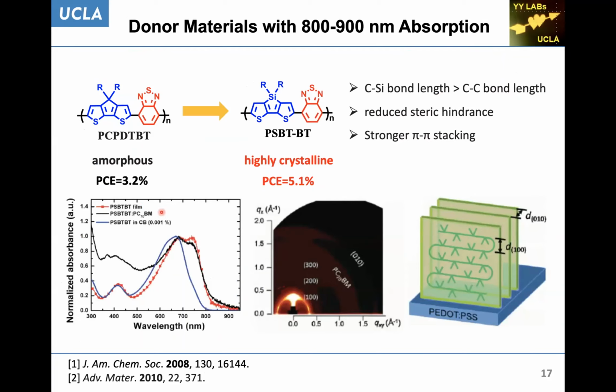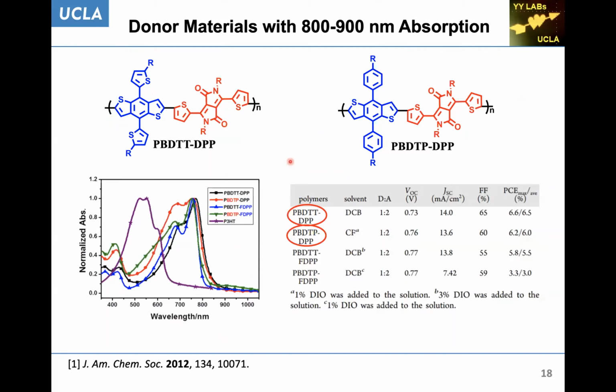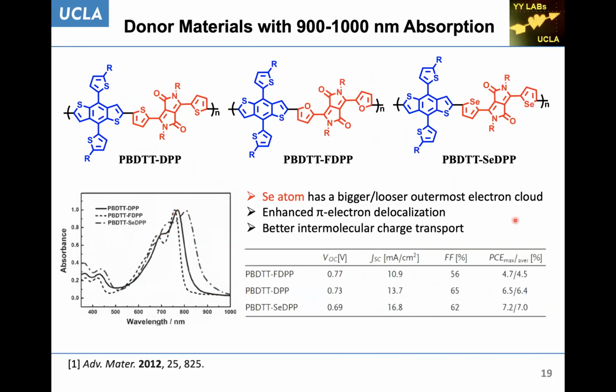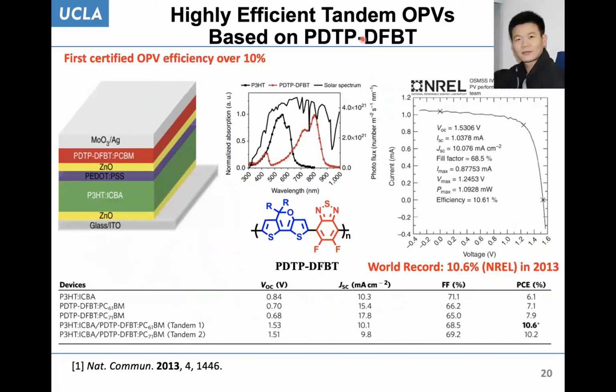You can see we start from a very low efficiency of 3%, and then we go to 5% efficiency. And then as we make the material more and more into the infrared, our efficiency also improves from 5 to 6%, and then to 7% now. So those are a series of developments in our group, and the really important part is Dr. Jing Biyu, now a professor in the Chinese Academy of Science in the Semiconductor Institute.